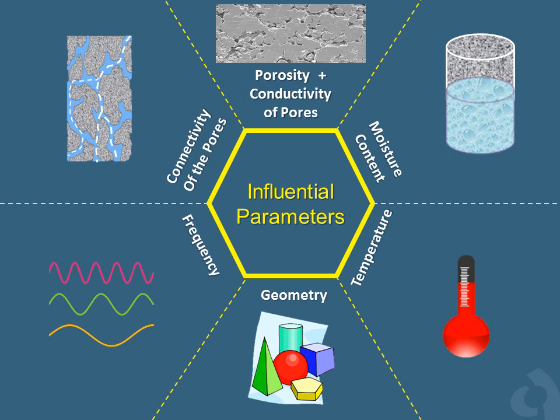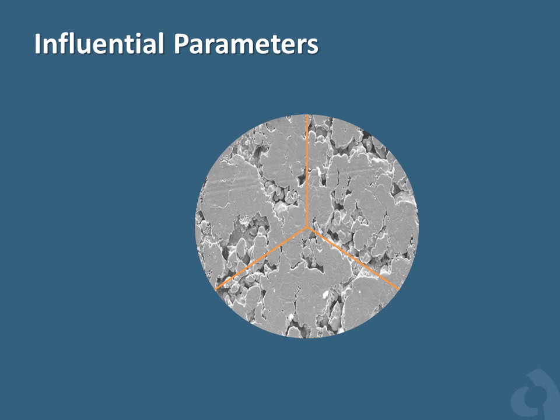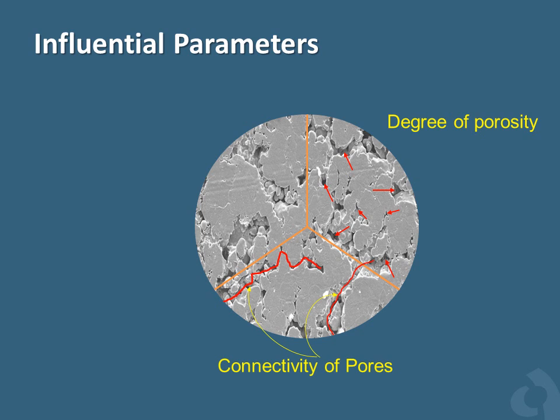However, if the effect of these factors is appropriately taken into account, any resistivity measurement technique should deliver the same resistivity value. The porosity of concrete can significantly affect the electrical resistivity measurements. The more porous the concrete is, the more space for ionic movement. In a big picture, these pores can make way for chemical agents to penetrate into concrete. We should also consider to what extent these pore networks are connected to each other, as well as the electrical properties of the pore solution, since the conductivity of pore solution can affect the total electrical resistivity of concrete.